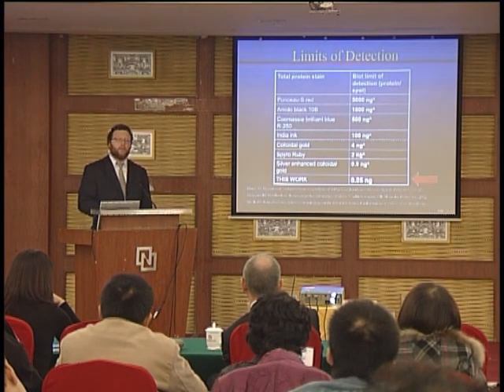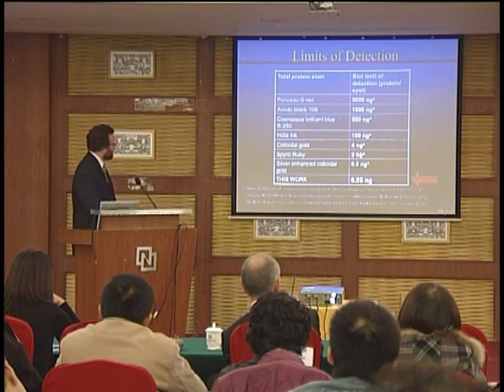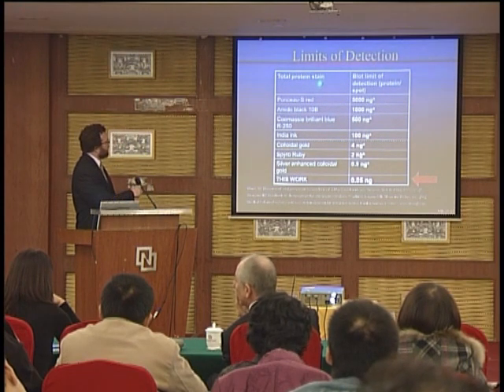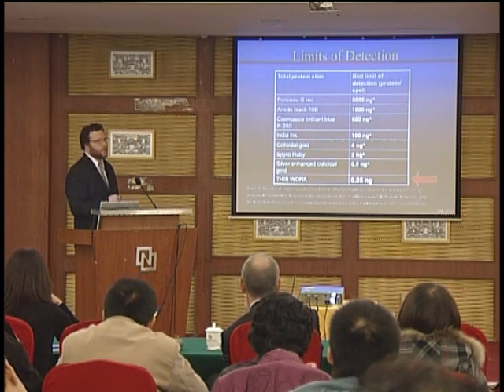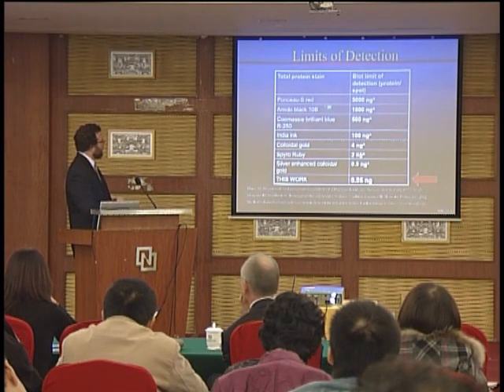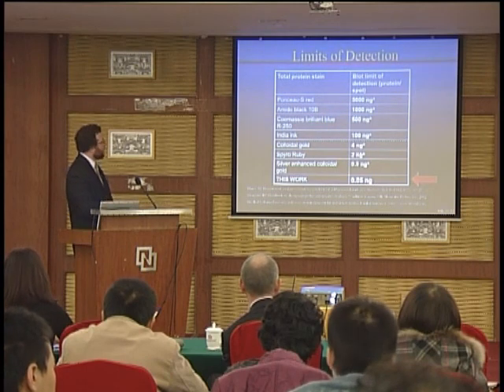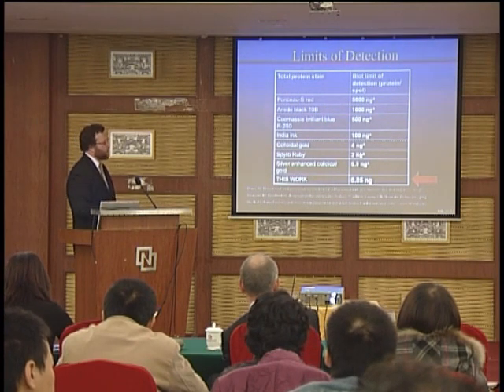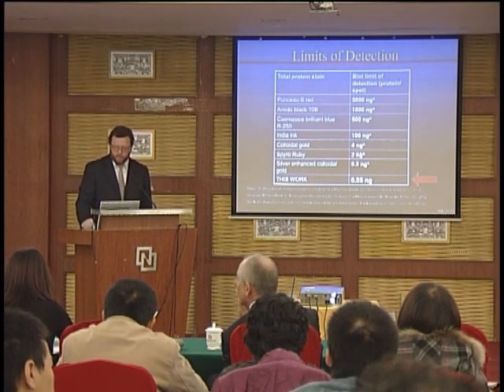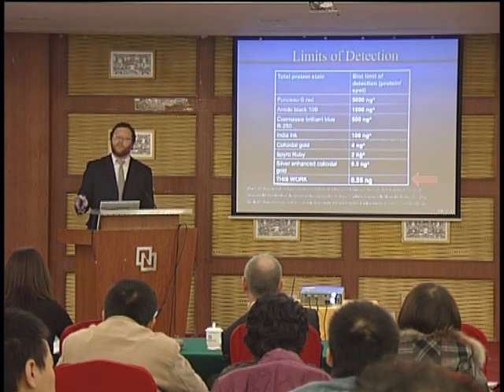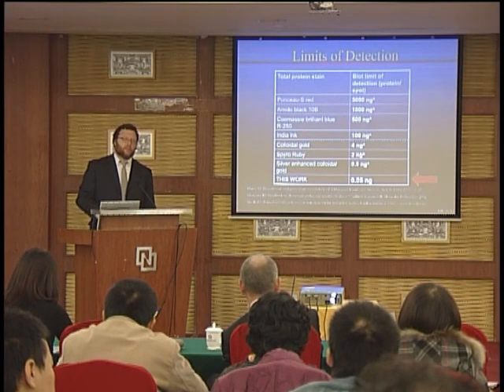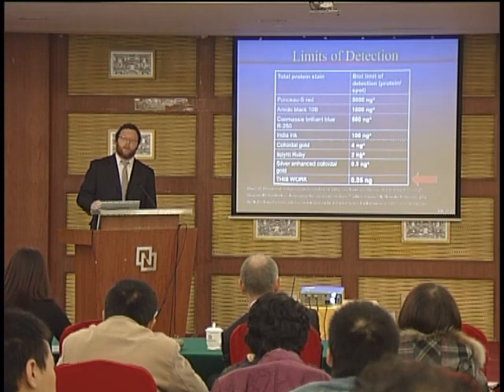In terms of the detection limits that we can achieve by this methodology, here we compare them with a number of different total protein stains typically used in biochemistry. These, in many cases, are what are typically used in wet chemistry laboratories. We're down here at about 0.25 nanograms as our minimum detectable quantity. Now this is using silver staining, which is the de facto methodology used in a lot of biochemistry labs.